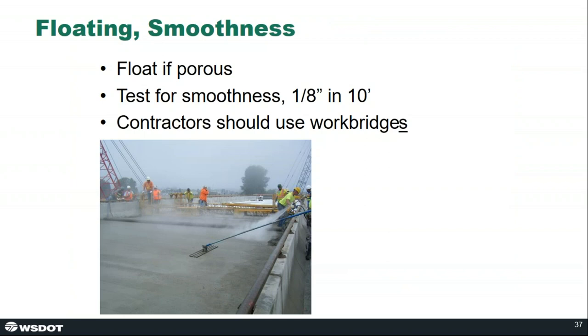And following that, we require floating if there's still porosity on the top or lack of consolidation on the top of that bridge deck surface. We do test for smoothness at this point while it's still plastic, and we're looking for an eighth of an inch tolerance over 10 foot. That's usually just measured with a 10 foot straight edge. And we generally encourage contractors to do this work from work bridges, and that's essential for wider bridges.